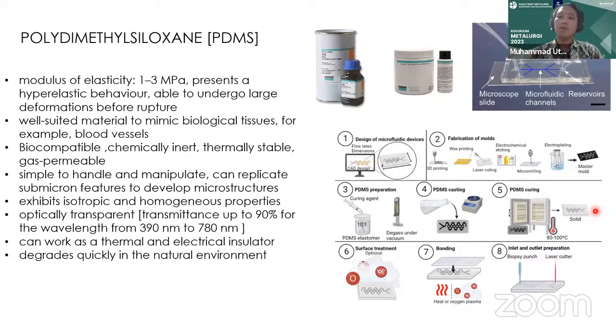And then, when we have the PDMS mixed with the curing resin, we can put it at room temperature for like 48 hours, or like 2 days, and then it will get solidified. But if we want to get it solidified faster, we can put the PDMS into an oven at 80 to 100 degrees Celsius for 2 to 4 hours, and then we can have this solidified PDMS. Then we can cut and peel the PDMS from the silicon wafer, and then we can bond the PDMS on, for example, a glass slide of this microscope slide, and then we can have this kind of working microfluidic device made from the PDMS.